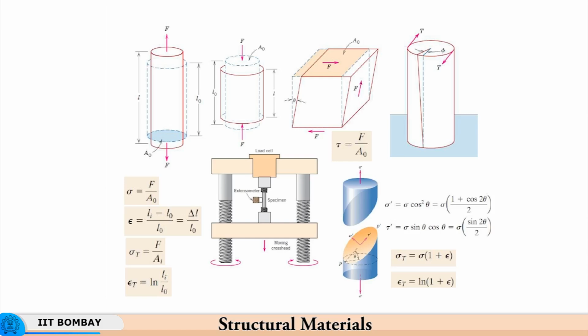So, the normal stress on this plane, similar to the normal stress over here. The normal stress on the inclined plane is given by sigma cos square theta. Why? Because you have this load divided by area. The component of load is F cos theta in this direction, and this cross sectional area is equal to A divided by cos theta. So, supposing this area is designated as A, then load divided by A is my true stress sigma.